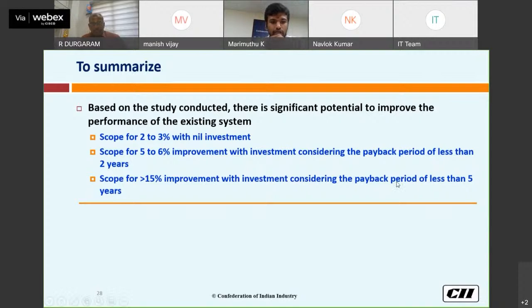This is to summarize. Based on the study conducted, there is significant potential to improve the performance of the existing system. We have scope for 2 to 3% with nil investment by studying the existing performance parameters, and with a payback of 2 years, there is scope for improving 5 to 6%. Also there is scope for greater than 15% improvement with a payback period of less than 5 years.